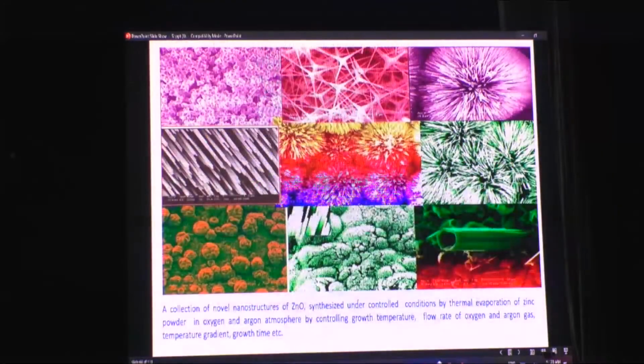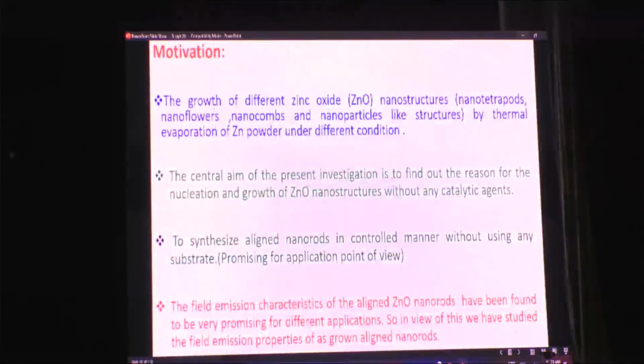Because we have developed different types of nanostructures using very simple techniques. We adopted the vapor deposition technique, and with its help we developed various wonderful structures by controlling the flow of argon, oxygen, and the amount of zinc. The melting point of zinc is very low, nearly 400 degrees centigrade.